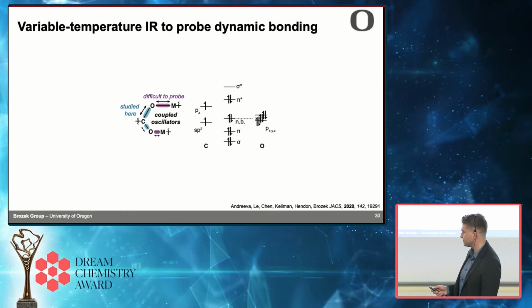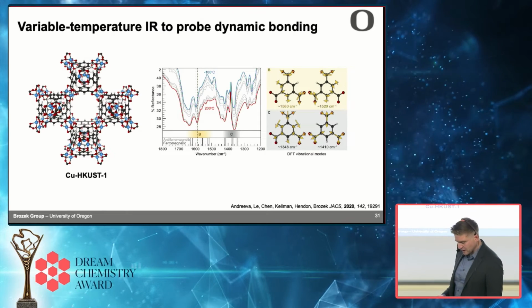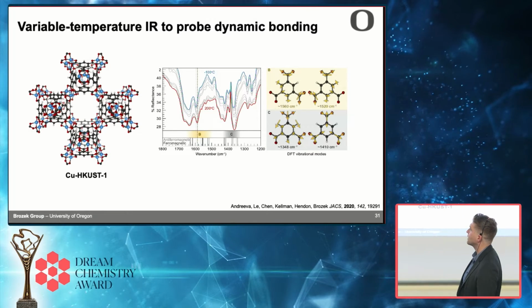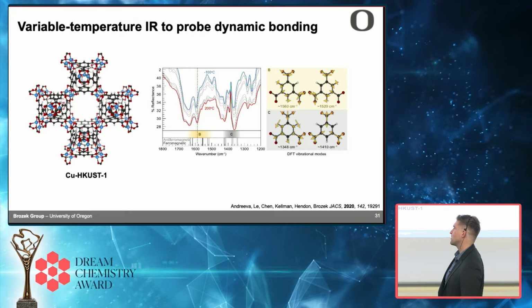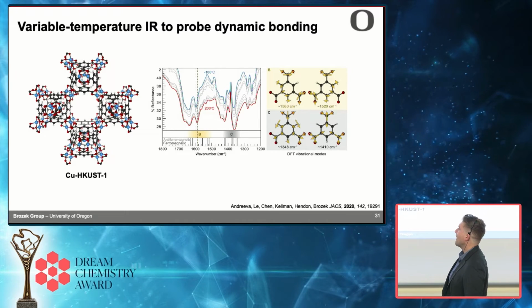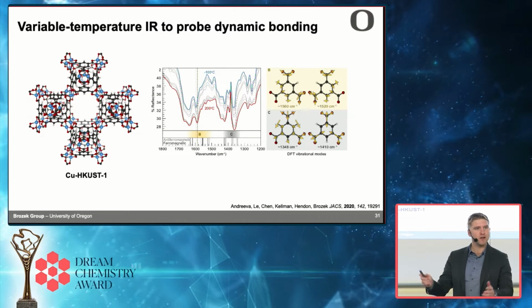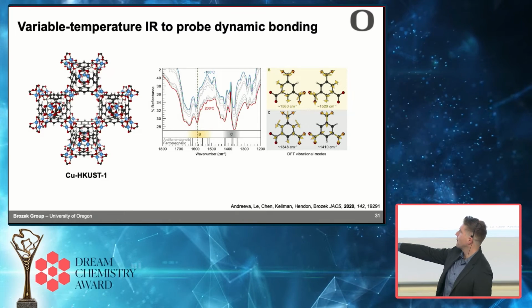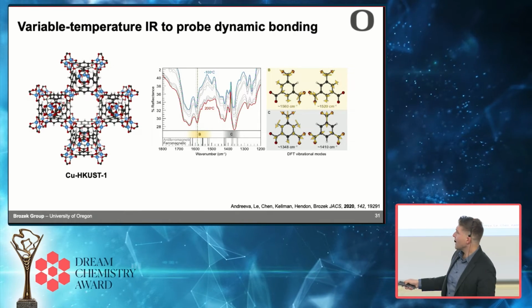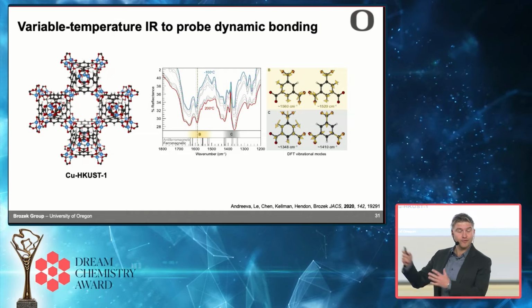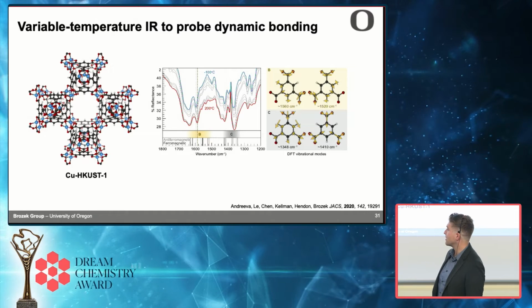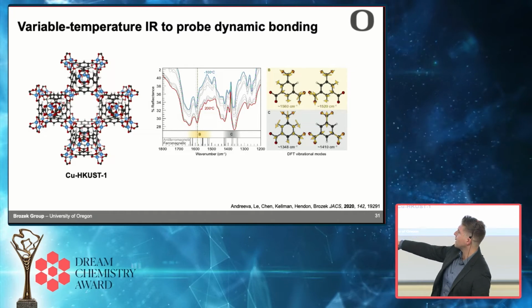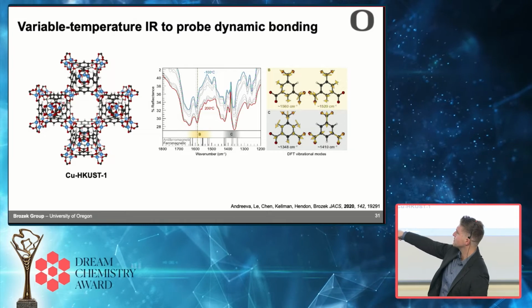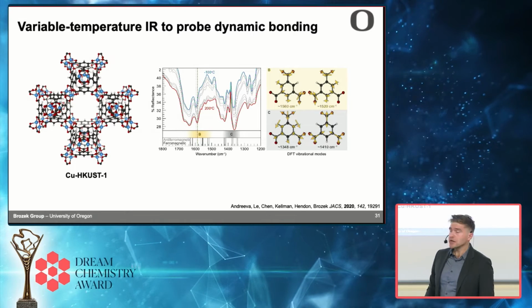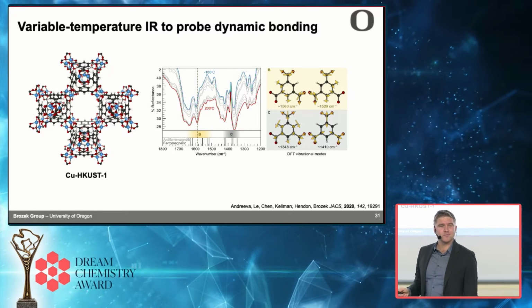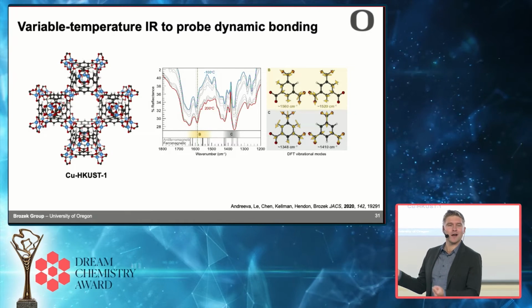That was the expectation. And so that's the experiment we did for 12 or so of the most common MOFs out there. Here again is our workhorse copper HKUST-1. And when you measure its IR spectrum across different temperatures, this is what the data looks like. And I'm looking at this, and there are a lot of IR bands here to analyze. I figured this is probably the asymmetric stretch, this is probably the symmetric stretch, and they redshift, but so do a lot of other bands.